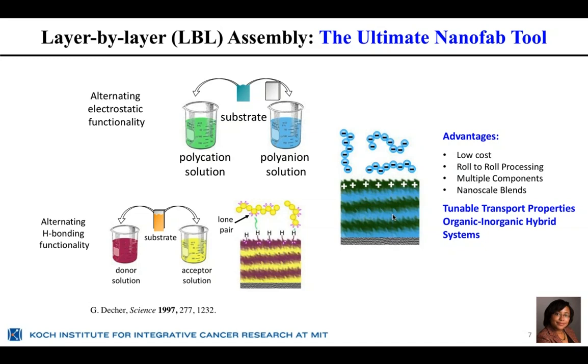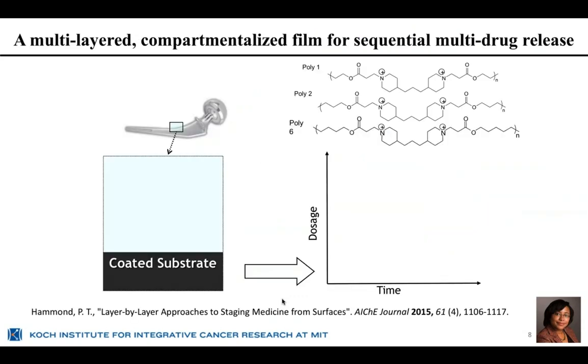Although you can use alternating charge to build these films, you can also use other kinds of secondary interactions, such as hydrogen bonds, and introduce hydrogen bond donors and acceptors in these kinds of layer-by-layer assemblies, along with a number of other interactions. Now, the reason that we're interested in this process for biomaterials is that it's a water-based process, and we can introduce a broad range of different biologic drugs, including proteins and nucleic acids. Now, you can imagine a more traditional drug delivery process. You might use something like a polyester. The contrast here is that many of our interesting degradable polyesters are only soluble in organic solvents. And those solvents can actually degrade or deactivate a number of proteins. And if we have to add heat to that to get a good solution, then you can also destroy your active component.